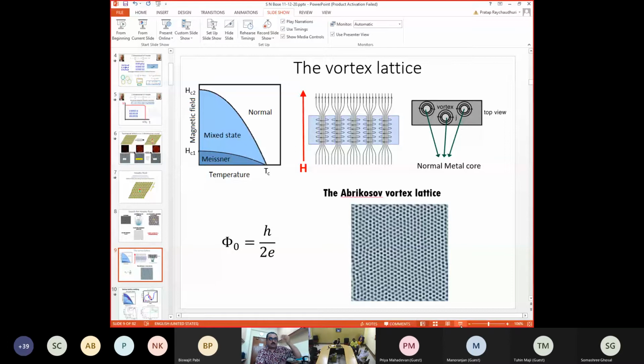Now this is looking at the superconductor from the side, let's say. If I look at it from the top, what I will see is that I have this circulating supercurrent, and at the center of this vortex, I have the vortex core, and this core actually, because of the magnetic field, has become a normal metal. So I have this normal metal core surrounded by a supercurrent. It is carrying a magnetic flux of one flux quantum, and these gray regions are of course superconducting.